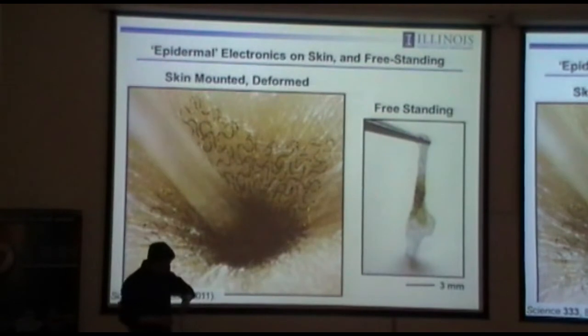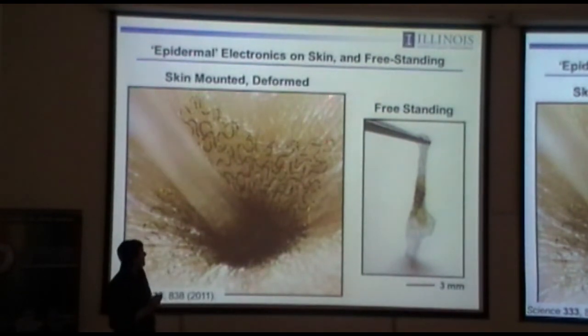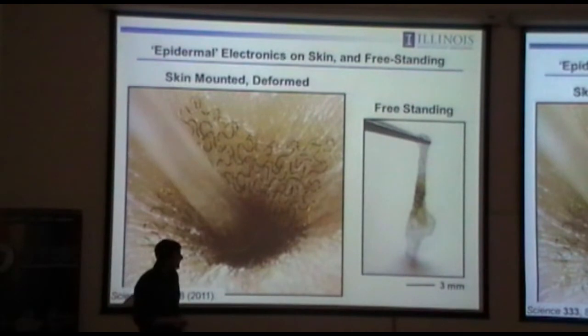So if you put it all together, you end up with devices that look like this. They laminate onto the skin. They're thin as the epidermis, mechanically matched to the epidermis, so van der Waals forces are strong enough to keep it adhered, even when the skin is severely deformed. So we put the device on the postdoc who's doing the work, and then we poked them with a glass rod and kind of see how that moves around. The skin kind of moves, and then the circuit just follows that motion, much like a temporary transfer tattoo.